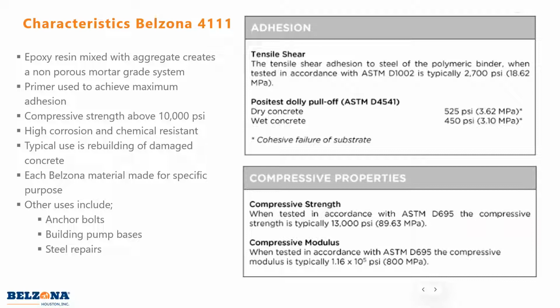So once again, our compressive property is typically 13,000 PSI, whereas most concretes are between 2,500 to 3,000 for high PSI concrete. So there's just many different things we can do with this. Not just typical rebuild of concrete damage, but we can also do some anchor bolts, building pump bases. We also do this on some steel repairs as well.